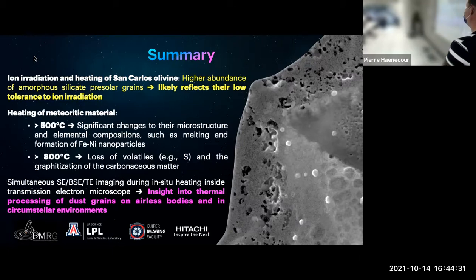One of the next steps that we are trying to do is to compare functional chemistry for organics. So try to see what's actually happening to the organics in terms of functional chemistry. If we look at organics, it's not just amorphous aromatic carbon. There is a lot of nitrogen, hydrogen. So we are trying to see what's happening to all those compounds as they're being heated. We know it's getting graphitized, but it's probably a lot more complex than that. So we are trying to combine it with EELS, or electron energy loss spectroscopy, so we can compare it as we heat the sample slowly and see what's happening to the sample.